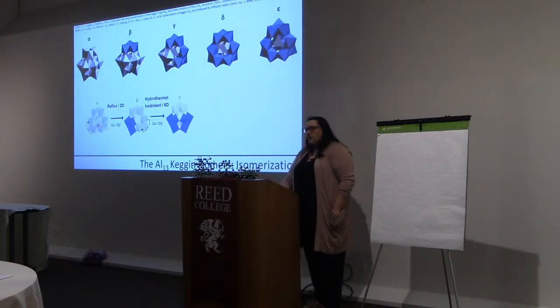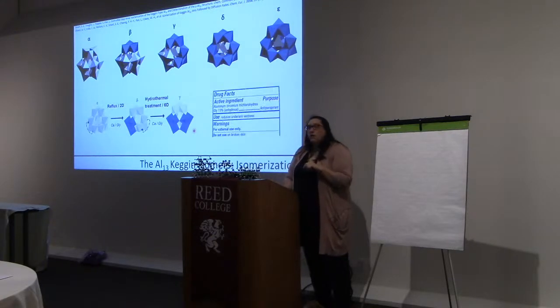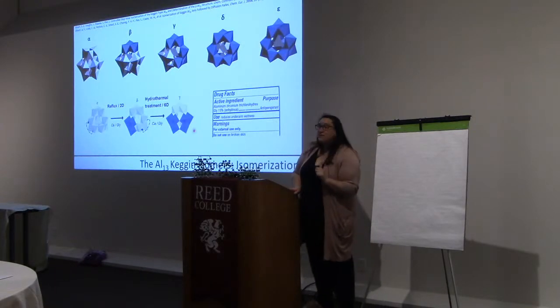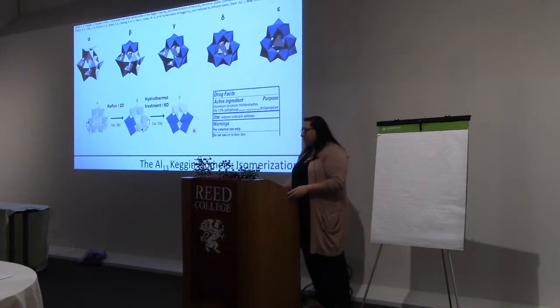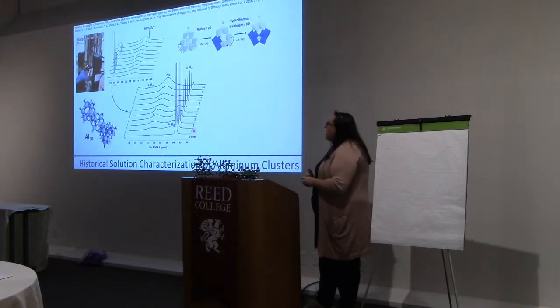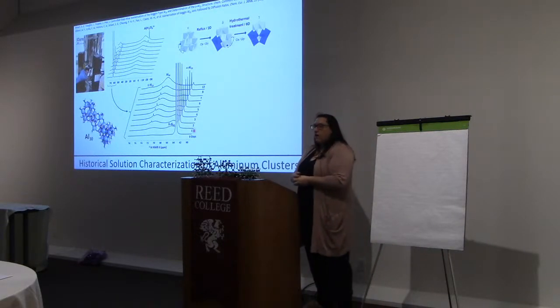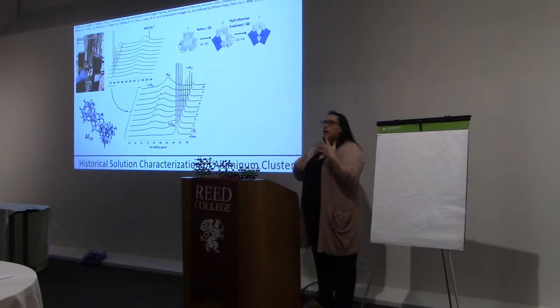If you take your epsilon and you heat it with calcium and glycine, you can isomerize to your delta after about 2 days, and then a week later, you start to get the gamma version. Why is that important? Well, in antiperspirants, we usually have glycine and calcium chloride. So we're looking at calcium, glycine, and heat, like the environment that you would have with antiperspirant, and we're getting this isomerization. So when I was at UC Davis in my postdoc, we had a collaboration with Colgate-Palmolive, and we were looking at this isomerization.